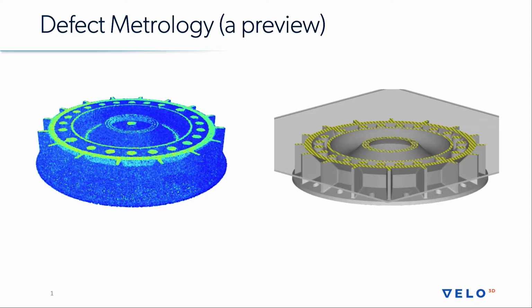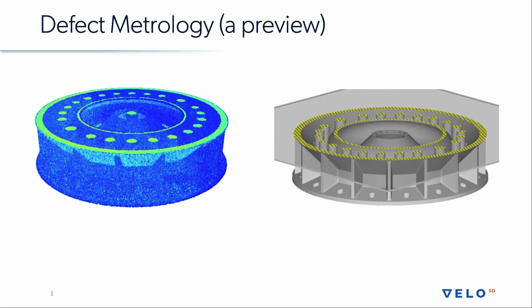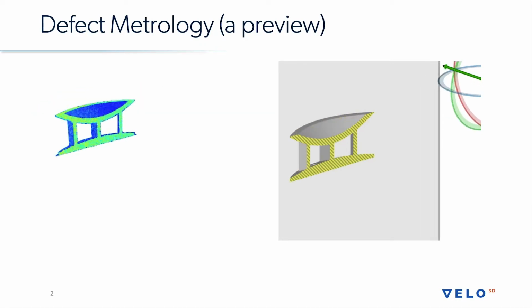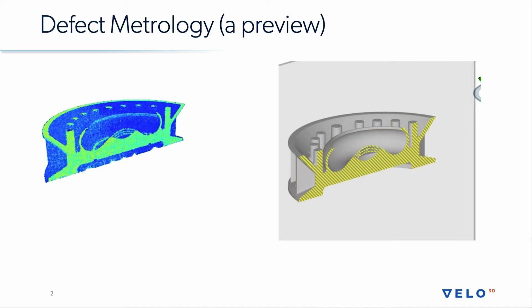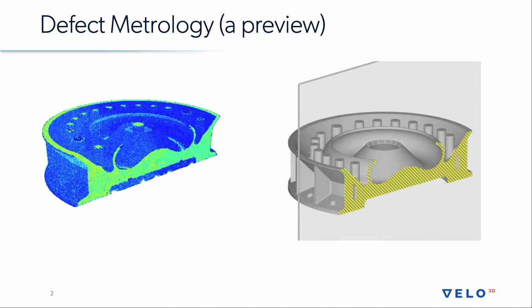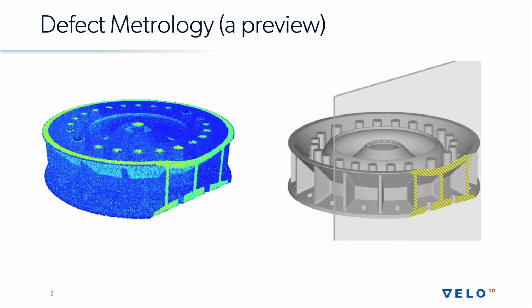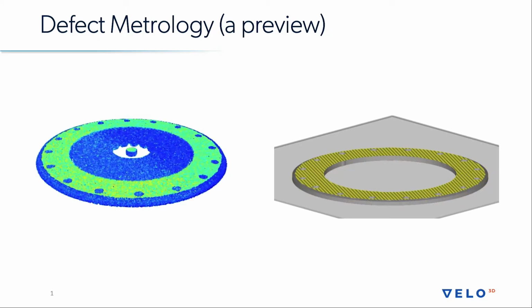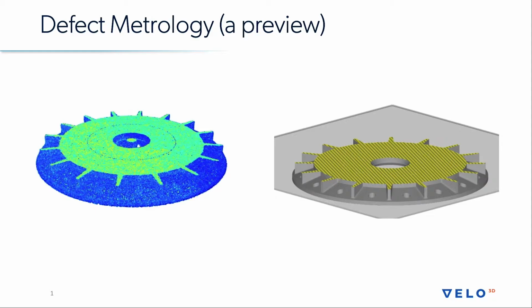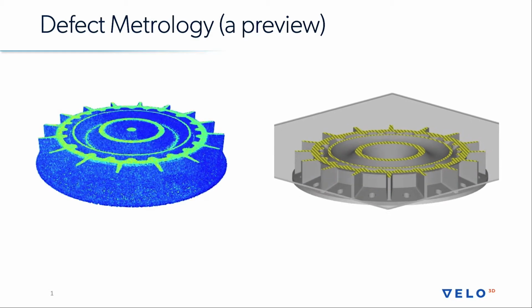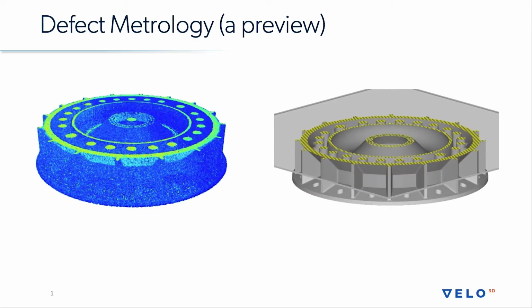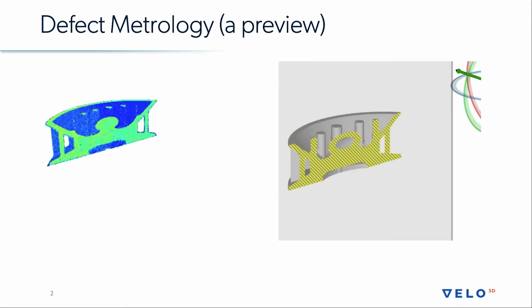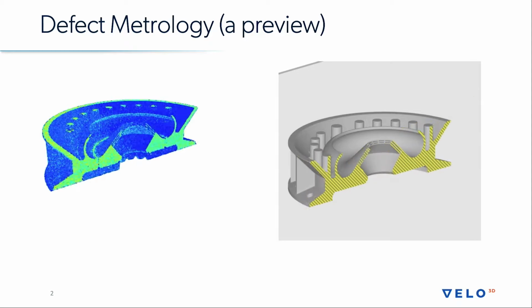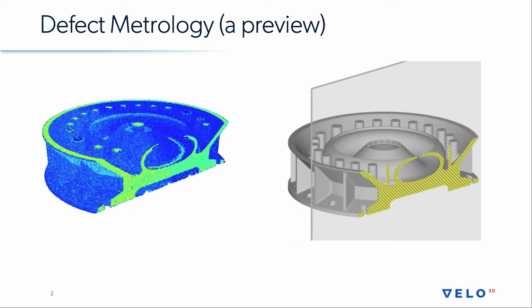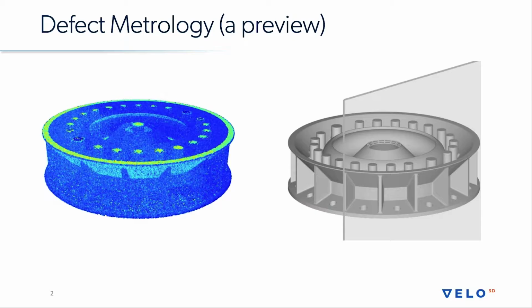This is not defect detection, but this is thermal data from the build. So this is kind of the thermal signal that we're collecting during the build, essentially kind of a virtual CT of the thermal data. And this isn't novel. There are a lot of companies that have this on the system. I think the thing that we're working on that we're super excited about and that we should be launching later this year is a real high correlation prediction of defects, of lack of fusion defects and surface defects that you could get from this data.